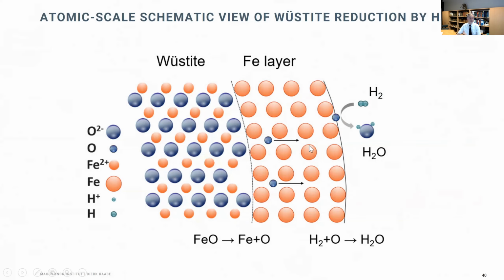And when you now translate this into a simple schematic, as is shown here, you have here the wüstite, the last oxidation stage that you need to reduce into pure iron. And this is, of course, this ionic lattice. And as you have a gradient in the so-called chemical potential of the oxygen from here to here, the oxygen leaves that wüstite, that oxide, and diffuses through this newly and freshly formed layer of bulk iron to the outside, where it would recombine with the hydrogen to form water. So the only exhaust gas here is water. And here you create the iron.